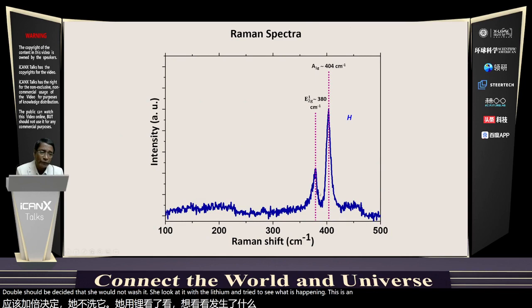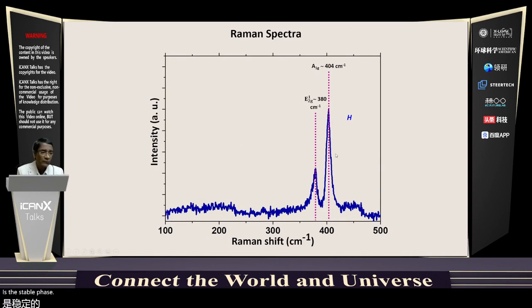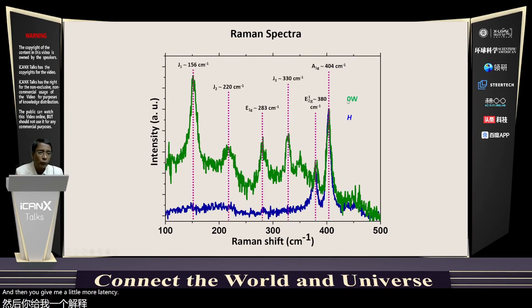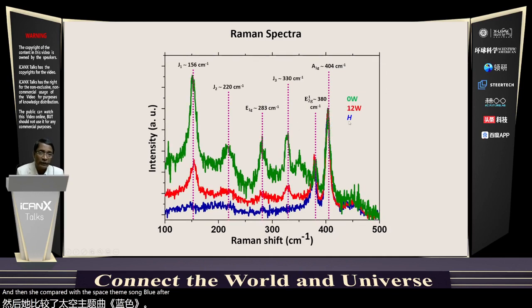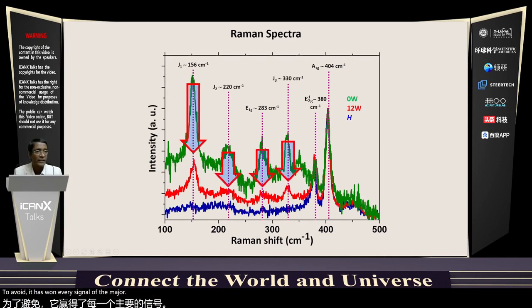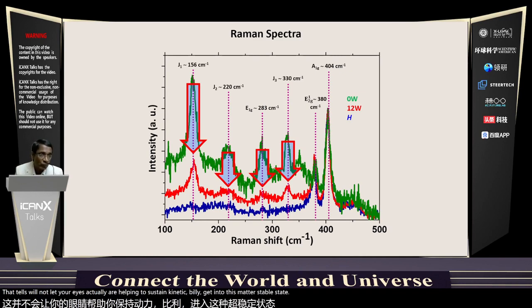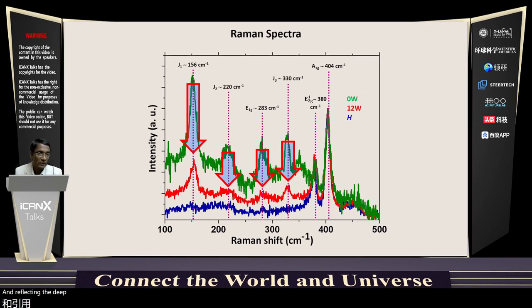This is the H phase that is the stable phase. And then the chemically exfoliated sample without any wash, zero wash, you'll see this notation, has this very intense signal coming from the metastable state. And then she compared with the very same sample after washing, 12 washes, and every signal of the metastable state is going down in intensity. That tells you that lithium ions actually are helping the system kinetically get into this metastable state and preferring the T prime state that you have configured.